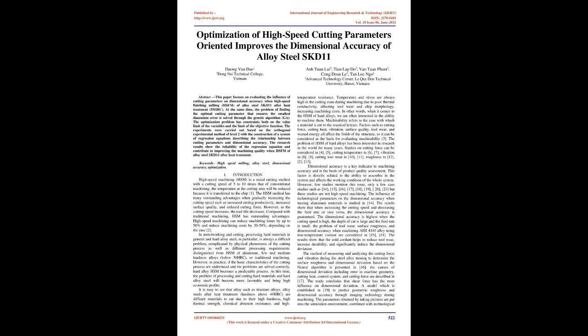The results show that the cold coolant helps to reduce tool wear, increase durability, and significantly reduce the dimensional deviation. The method of measuring and analyzing the cutting force and vibration during the steel alloy turning to determine the surface roughness and dimensional deviation based on the neural algorithm is presented in [16]. The causes of dimensional deviation including error in machine geometry, cutting heat, control system, and cutting force are described in [17]. The study concludes that shear force has the most influence on dimensional deviation.